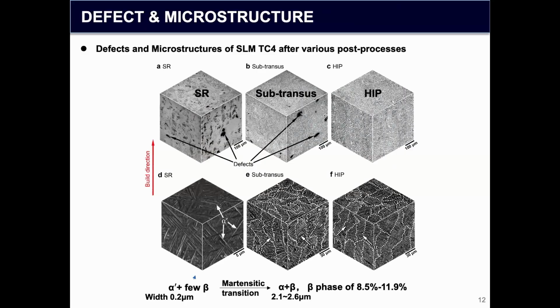So this is the defects and microstructure after the three types of processing. We can find that for the defects, for the SR and subtransus, there are still some defects inside the materials, but after HIP, there are no defects. And for microstructure, for the SR, we can find the main phase is the alpha prime martensite, but after the subtransus and HIP, we can find the phase is mainly the alpha plus beta phases, and the width becomes larger, and the beta phase is in the range of about 10%.